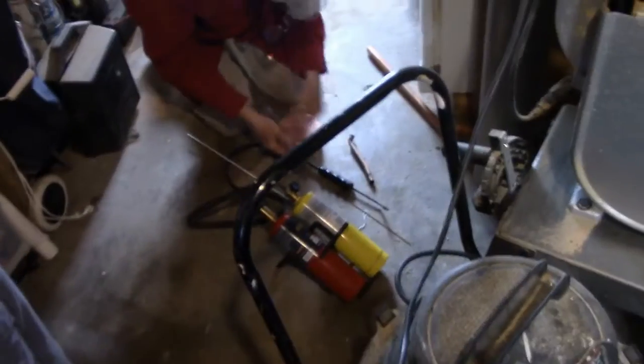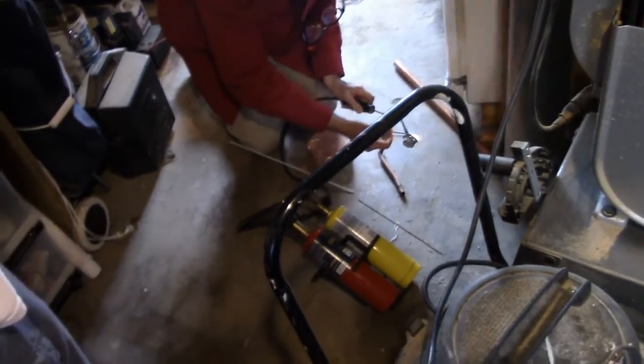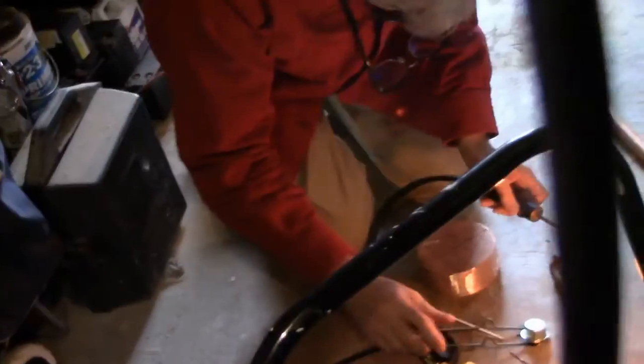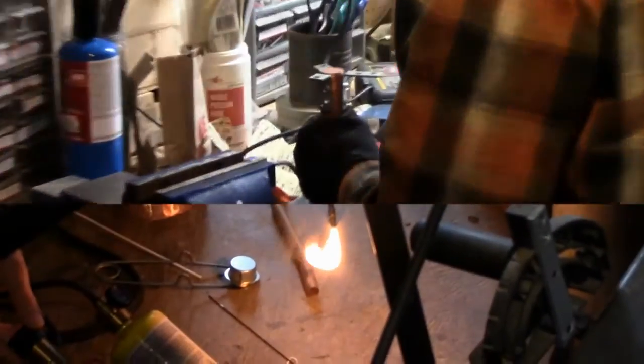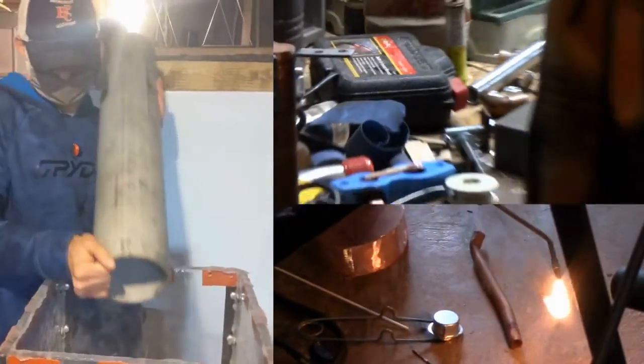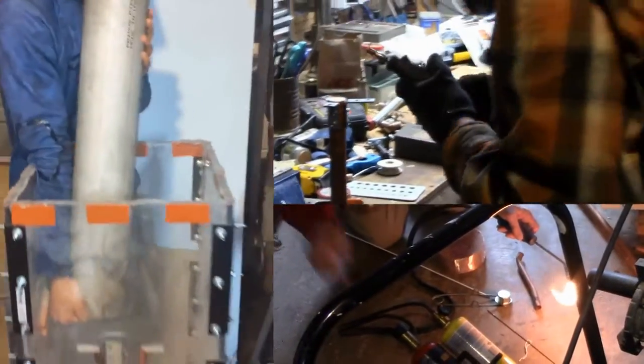Constructing the mock helical anchor without the ability to weld was very difficult. We originally tried soldering the copper, but the pieces were too large to get to a high enough temperature with the available blowtorch. Metal brackets instead were used to attach the HTB and inner copper rod, which then rested atop the outer copper pipe in the test rig.